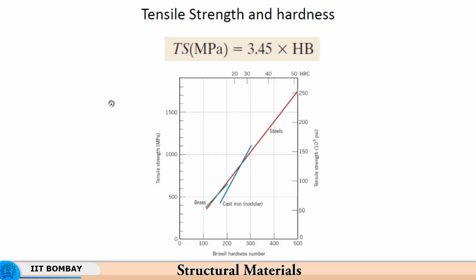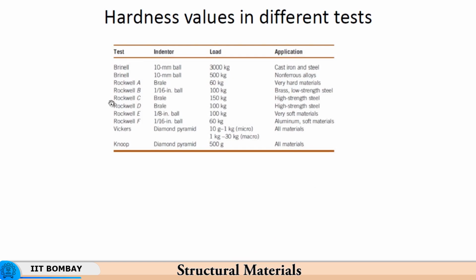I told you that the Rockwell scale will not relate with this, you have BHN, VPN etc. relating with this. So, tensile strength in MPa increases with the Brinell hardness number, and then you get different values of hardness for different kinds of materials. So, some illustrative values have been given over here. So, for example, you have a 10 mm ball with 3000 kilograms which is used for cast iron and steel, and these are for Brinell. For non-ferrous alloys, 500 kilos, as the materials are very soft.